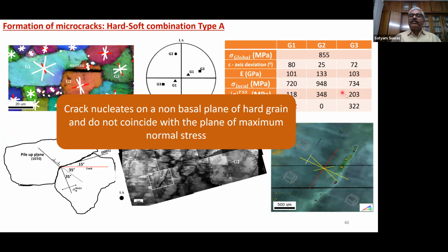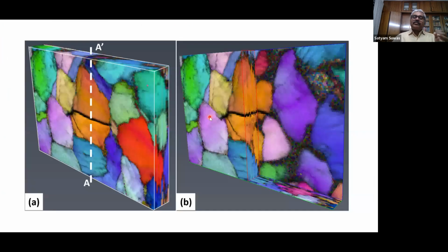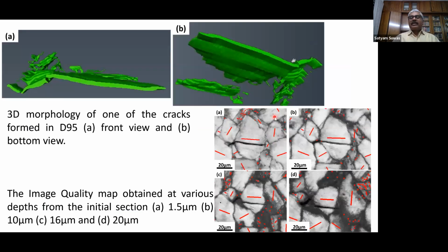And here, without going into detail, we did a similar kind of analysis and found that the crack nucleates on a non-basal plane of the hard grain and does not coincide with the plane of maximum normal stress. Now, there has been some theory that all the observations related to orientation, or any parameter not related to the combination of hard-soft orientation, could be misleading, because we see only one plane of observation. So if we see 3D microscopy, we could see the grain in which the crack is initiating, and what is the grain above this and below this. This exercise was also done, and even after examining the three-dimensional microstructure by FIB and EBSD, we could see a similar kind of trend.